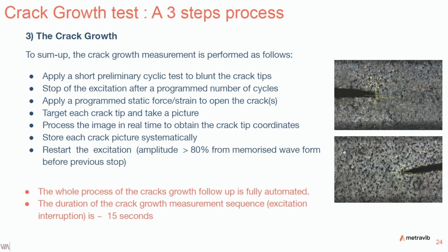Process the image in real time to obtain the crack tip position or coordinates, store each crack picture systematically, and restart the excitation. We can restart the excitation with an amplitude of 80% from the memorized waveform before the previous stop. So the whole process is fully automated. To give you an example, to follow 4 cracks at the same time, the duration of the crack growth measurement sequence is about 15 seconds.